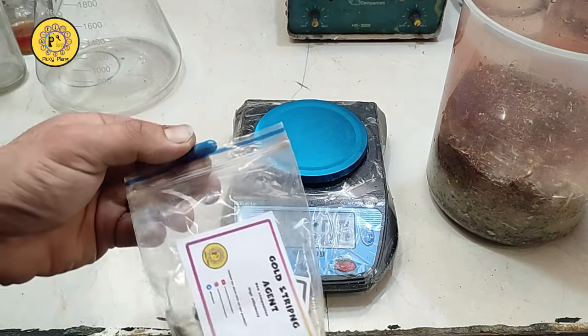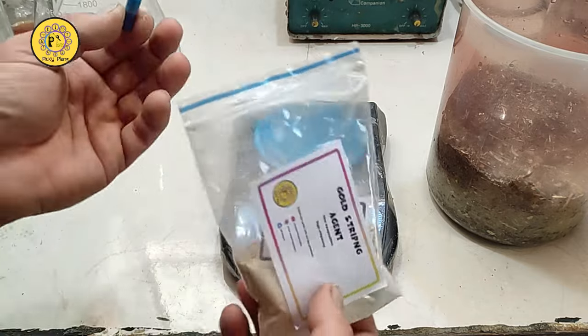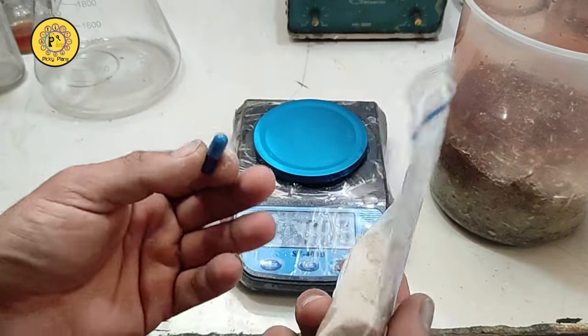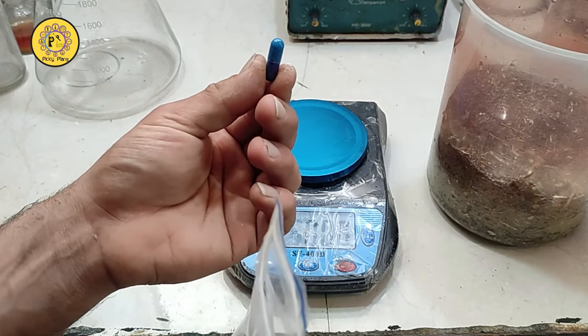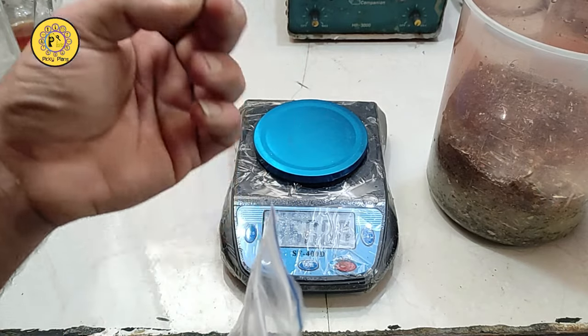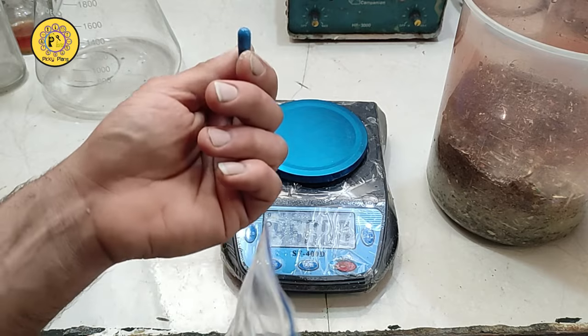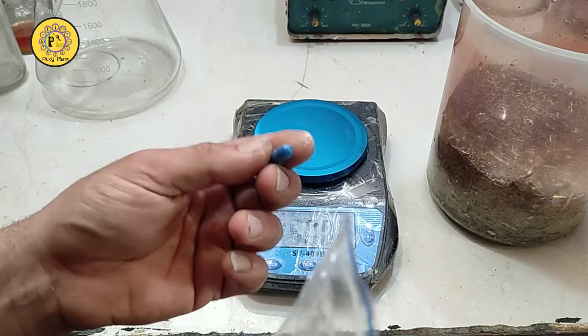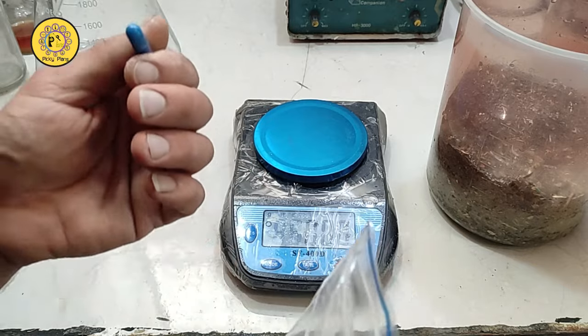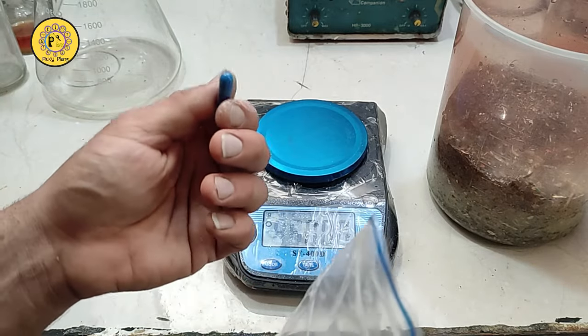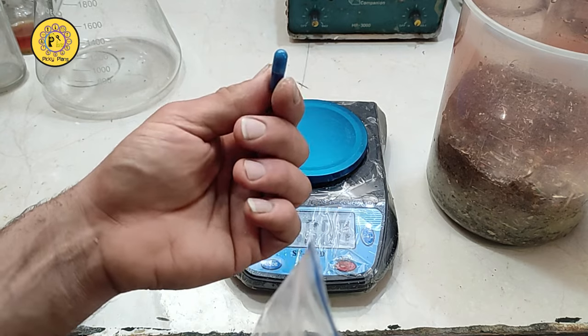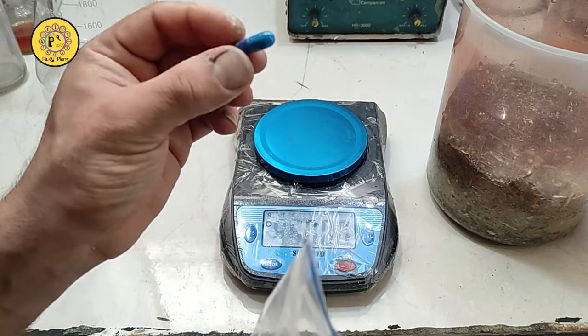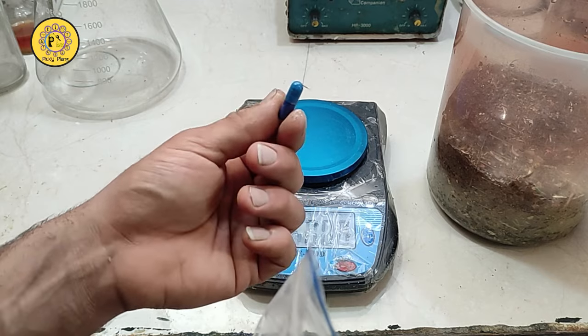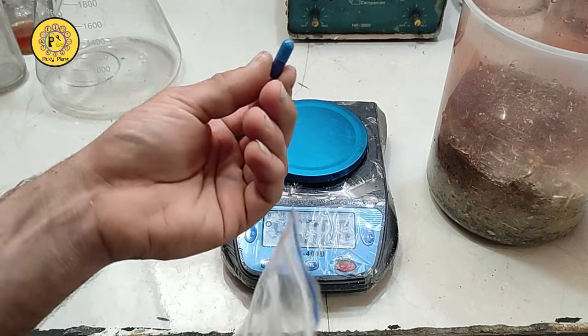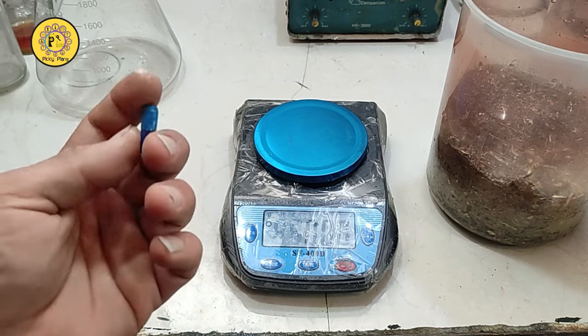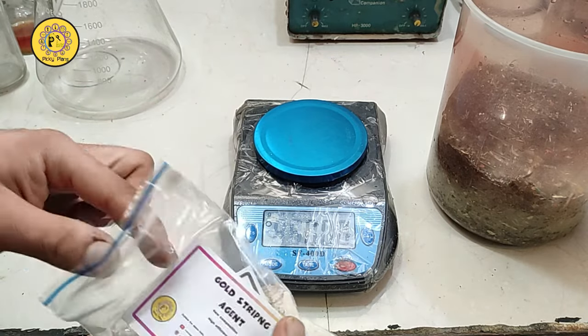And for my dear friends here, I'm going to explain what actually these are. This is a cap containing the powder, which I call a stopper, which stops the reaction when you are done stripping the gold. You want to reclaim your gold using zinc powder. You add this before processing with zinc. This will stop the further dissolution of gold in the cementation process.